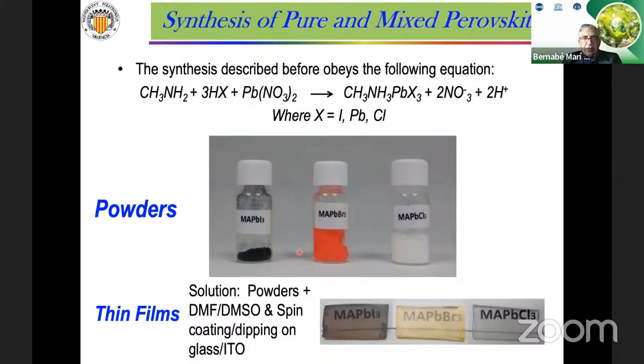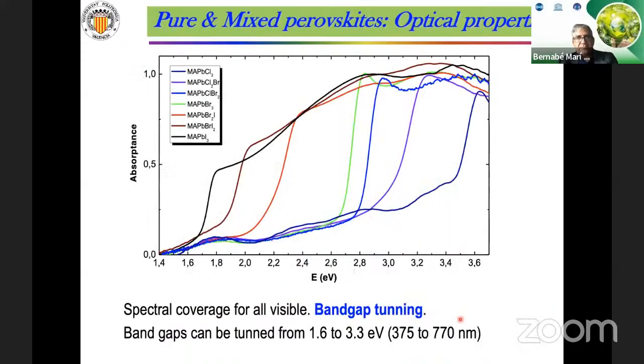So we are able to obtain powders, of different colors depending on the composition. In that case, methylammonium with lead, iodide, bromide, or chloride. Or we can also produce thin films if we dissolve these powders into organic solvents like dimethylformamide or dimethyl sulfoxide, and then, by spin coating or dipping, we deposit these materials as thin films.